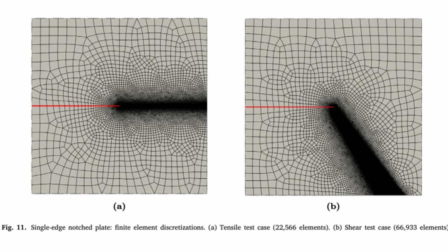And does this gradient-based approach have other benefits? It does. It has a dual function, really. First, it acts as a brake. When the simulation hits an unstable patch, like rapid crack growth, the line search will naturally find a step size lambda less than 1. It shortens the step, preventing the solver from overshooting and diverging. This provides the needed stability. The safety net. The safety net, yes.